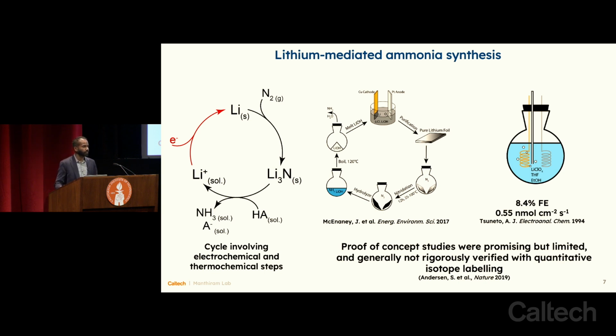They demonstrated a greater than 80% Faradaic efficiency for making nitrogen into ammonia. Faradaic efficiency is defined as the fraction of electrons that go toward your desired reaction. So if it's 80%, then 80% of the electrons went towards making nitrogen into ammonia. This is pretty good from an electron-based selectivity perspective. But we can probably all agree that we're not going to feed the world with a reaction that involves solids. Solids handling is really challenging, and we have macroscopic chunks of lithium metal here, which we really want to avoid, right? We know that there's a safety hazard in having large pieces of lithium metal. So even though this is a good proof of concept, there are a lot of issues with this implementation.